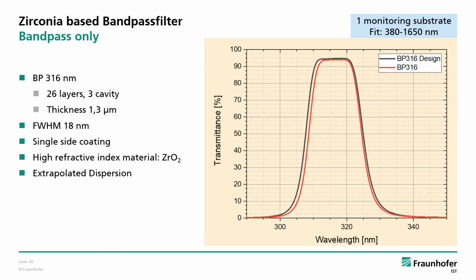Also for the process with zirconia that was used for 316 and 327 nanometer, a nearly perfect match could be realized using the broadband monitoring. The wavelength range for the transmittance measurement was only from 380 to 1650 nanometers, and thus we used only an extrapolated dispersion without a huge effect on the bandpass.